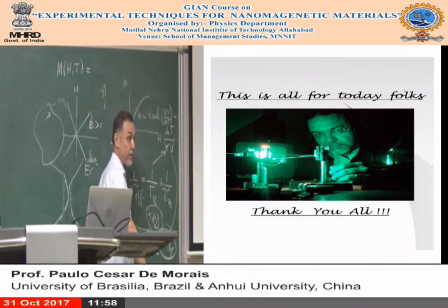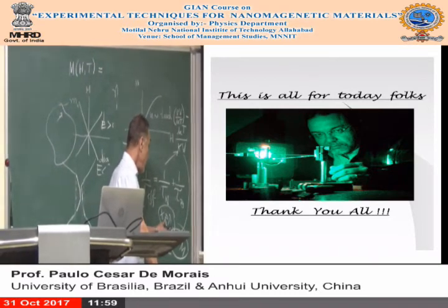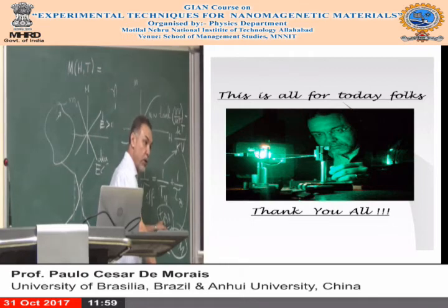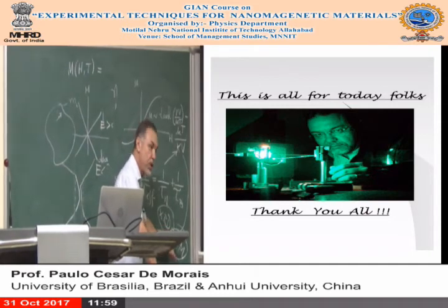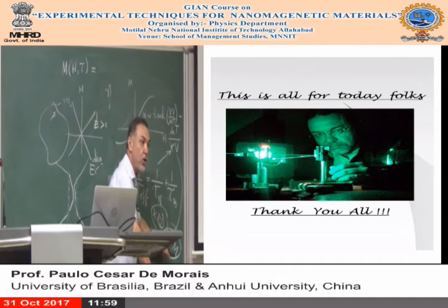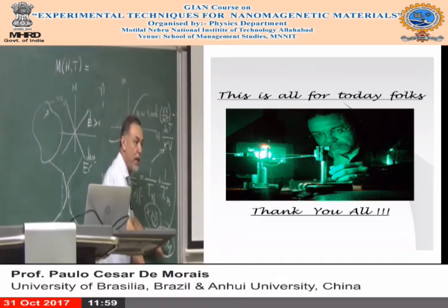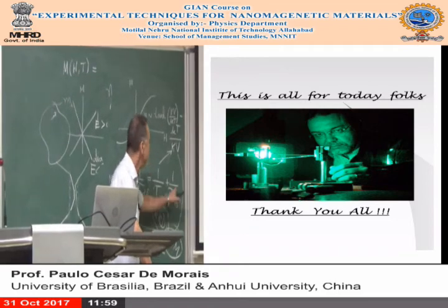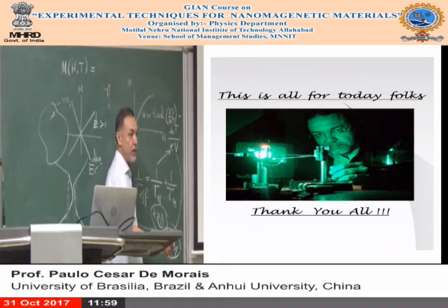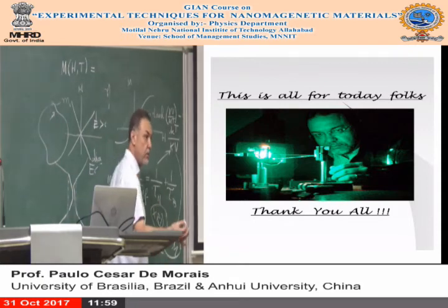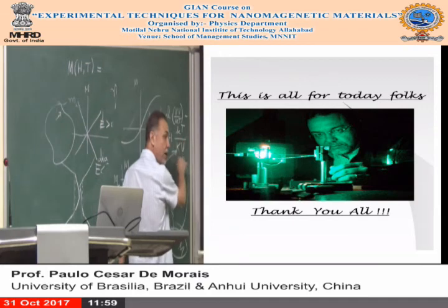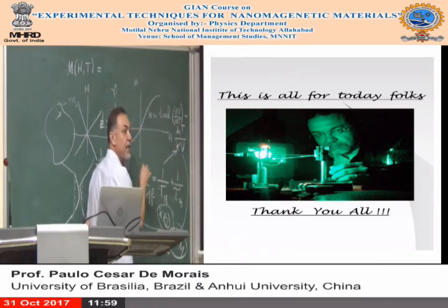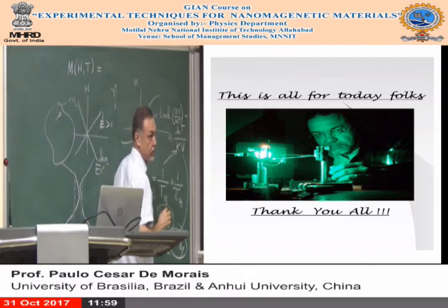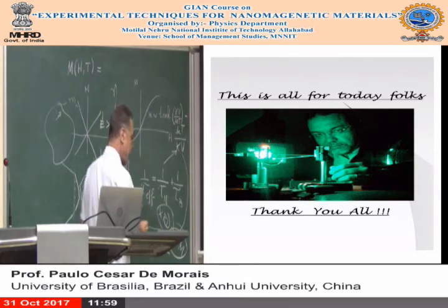From the X-ray diffraction, doing Rietveld refinement, you can extract the size, the volume. If that volume is close to this one, it means the shell layer is very thin. So basically, the physical volume will be the magnetic volume. It's a way to check this. But in principle, your question is, can we extract anisotropy from standard VSM? Yes, you can, but it's an indirect way to measure. Yeah, exactly.